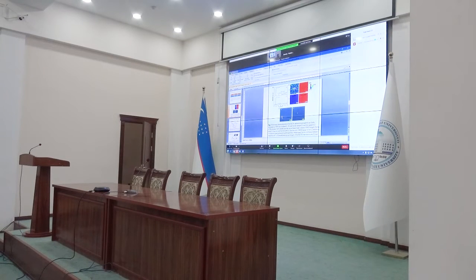You can see the top part, L1. You can see this is smooth, no other direction, one color. Okay, and this is an image of electron beam backscattering diffraction. While in sample L2 you can see different colors. This shows that the crystal consists of domains, and these domains are rotated by 60 degrees.